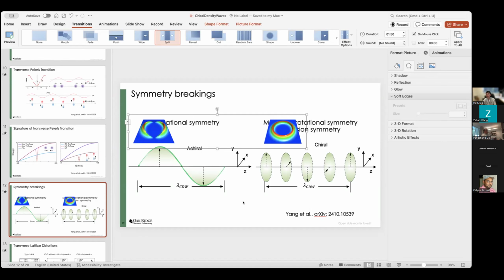I see. So you're basically saying, but then you say this is highly coupled with the spin. It doesn't couple to spin, it's just the lattice distortion. So think about the tellurium single crystal. Tellurium is well known as a chiral structure, right? The atoms form a triangle if you look from the top, but if you look from the side, they chirally go up. You can imagine at a very high temperature, it's just a 1D string, and then as you cool down, it's displaced in a chiral way. So in this case, it's purely lattice that does that. It's purely lattice, yes. There's no coupling with the spin.